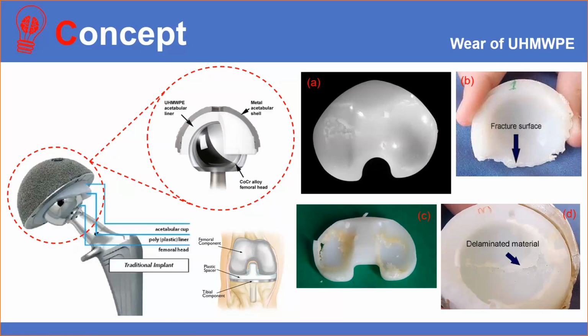So in 1962, ultra-high molecular weight PE came into the picture, a similarly low-friction but much more wear-resistant polymer with remarkably better performance. From then on, arthroplasty has known considerable evolution, but ultra-high molecular weight PE remains the gold standard for artificial hips, knees, and shoulders. However, it has been demonstrated that the main factor responsible for the failure of ultra-high molecular weight PE in joint replacement is oxidative degradation, which decreases its mechanical properties, including the abrasive wear resistance. This leads to the formation of wear debris and consequently to osteolysis, which has been recognized as the main cause of failure in orthopedic implants.